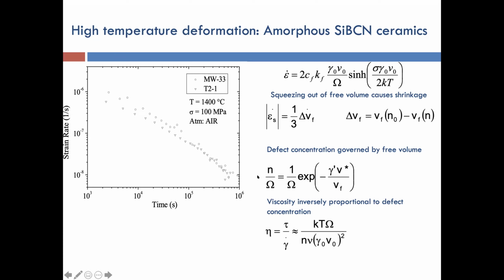But coming back to the science part of it, even after about 300 hours of operation, the strain rates are low, in the order of around 10 power minus 9. That means the material is hardly deforming, even after 300 hours of operation. So that's what it means when I say we are talking about strain rates in the order of 10 power minus 9 per second.